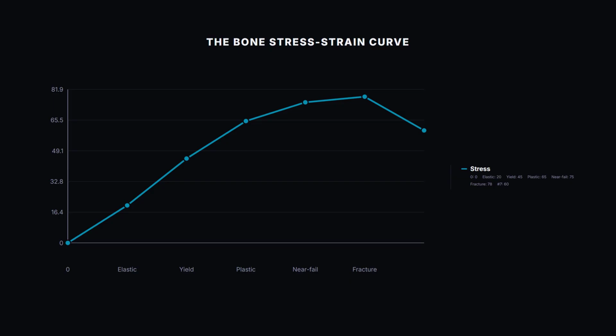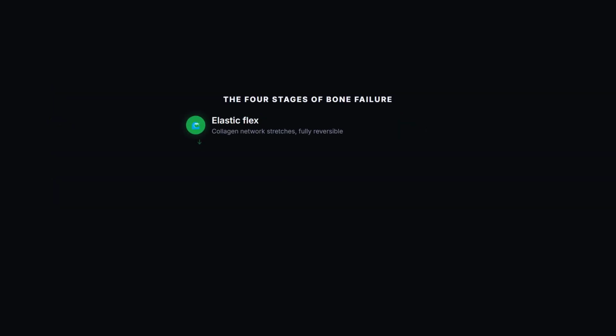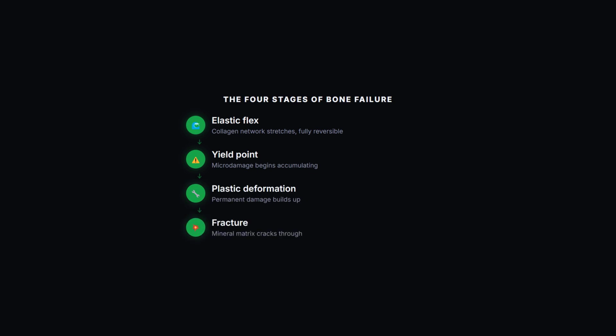Push harder still, and you hit the fracture point, where the bone finally gives way. Walking through that curve stage by stage. First, the collagen network stretches, and the whole structure flexes elastically. Next, at the yield point, microscopic damage starts accumulating faster than it can be absorbed. Finally, the mineral matrix, which can't stretch nearly as much as collagen, reaches its limit and cracks propagate through to complete fracture.